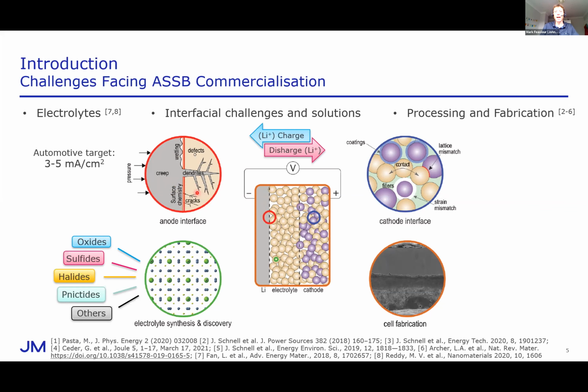If there's any mismatch in that transport process, you will end up with perhaps stripping out of lithium from your anode surface, leaving voids, increasing the current density beyond critical levels, and causing all sorts of problems, including dendrite formation. These are thin filaments of lithium which can grow and penetrate even the densest of ceramics over time, leading to short circuits and cell failure. The kind of automotive targets we have at the moment are 3 to 5 milliamps per square centimeter, which is well above most of the academic literature. I'll come on to cathodes a little bit later.